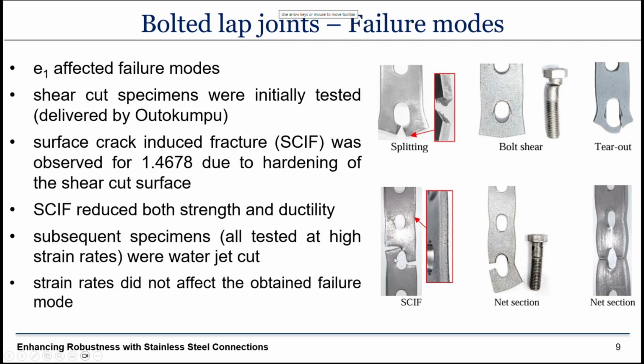We termed this sort of fracture surface crack-induced fracture, and the reason for that was that the company that donated the specimens for the lap joints used shearing as a cutting method. So there was a lot of localized hardening and some micro cracks induced. For the 1.4678 specimens, that did lead to a reduction in ductility and strength. So we did afterwards test some water jet cut specimens and the response was identical.